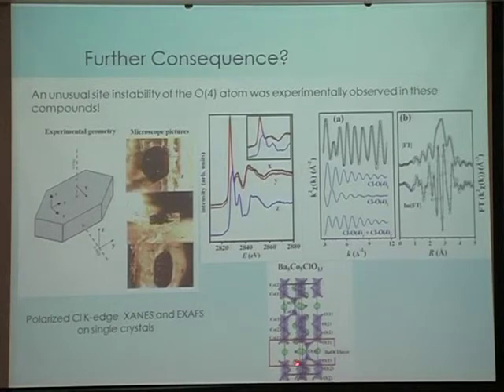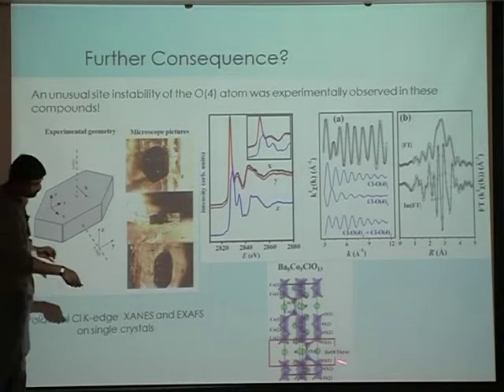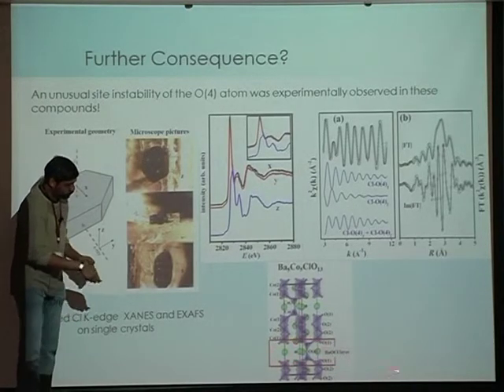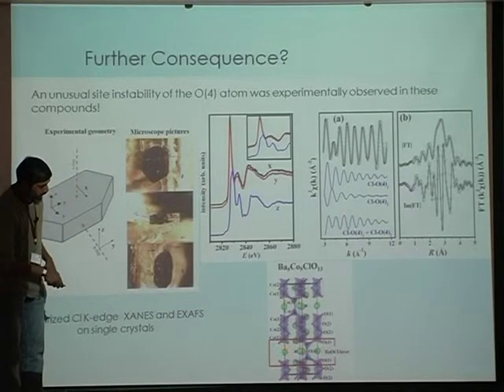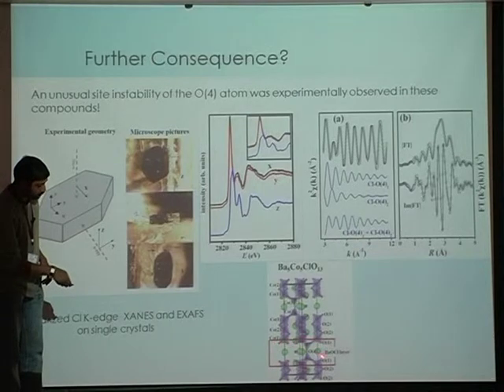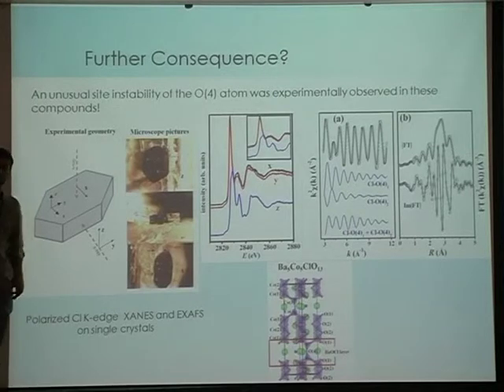What we try to do is first look at this structure and look at this BaOCl layer. What we thought is: let's do chlorine, a unique atom sitting at this plane, which is nowhere else other than this plane. Do chlorine XANES or EXAFS, look at the local structure and find out what happens to the O4. At least we can look at O4, that particular covalency.